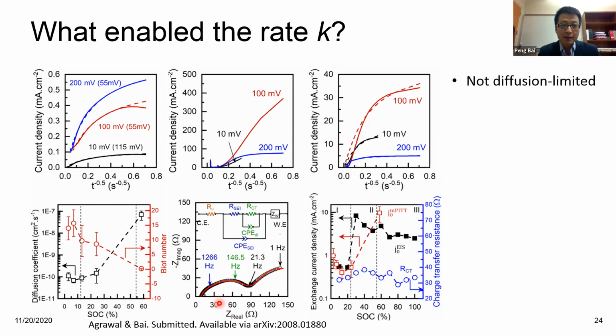The first one is that, looking at the top row, this is the current versus the reciprocal of the square root of t. The reason for this special arrangement is the way to analyze this current density: if you believe it's a diffusion limited case, you should use the Cottrell equation. The Cottrell equation gives you this relationship. When you have this plot, if it indeed follows the Cottrell process, a diffusion limited process, you should have straight lines. But as you can see here, we don't have straight lines. So that means it's not diffusion limited.